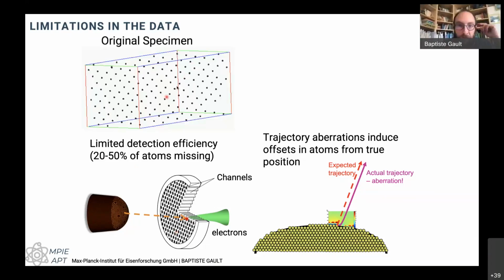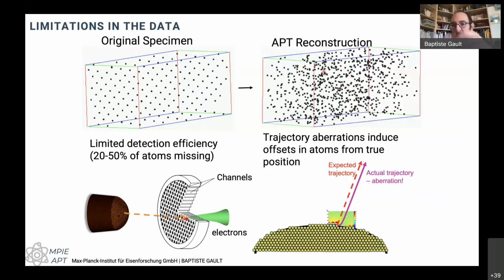But if we have a specimen where atoms are perfectly arranged on the lattice like this, after the field evaporation process, collection of the data and reconstruction, often we get a sort of mishmash of points like this. And it's not fully bad, right? I'll get back to some of this afterwards. We still have a very good resolution. But sometimes it's kind of difficult to answer the typical question of what's the resolution, because these trajectory aberrations are not controllable in some ways. So it's not like we can make an aberration corrected atom probe anytime soon.